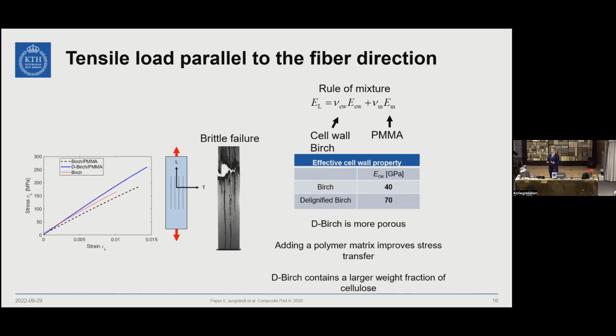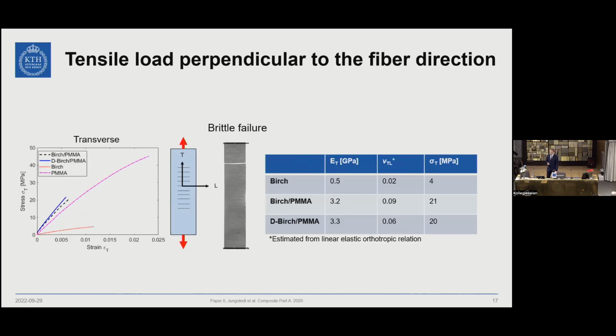So we believe that adding a polymer improves the stress transfer. You can also see from the strain fields the content of cellulose is much higher in the delignified birch. Now, if you do the same thing but in transverse direction, we can see that there's a drastic increase in elastic properties. So adding a polymer is better for the elastic properties, and the same thing for the strength. Same here, we get a brittle fracture with quite a linear behavior until fracture.